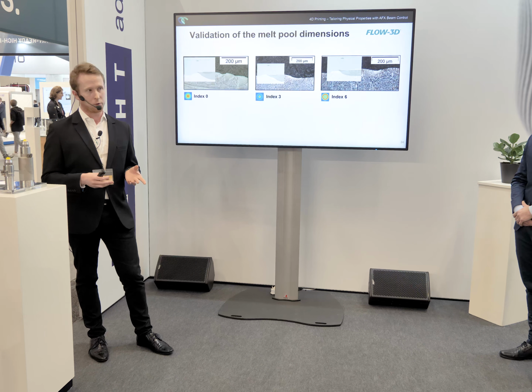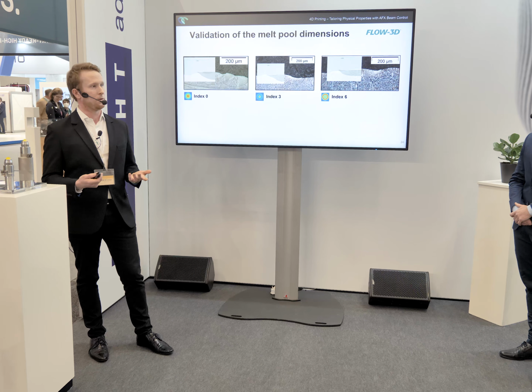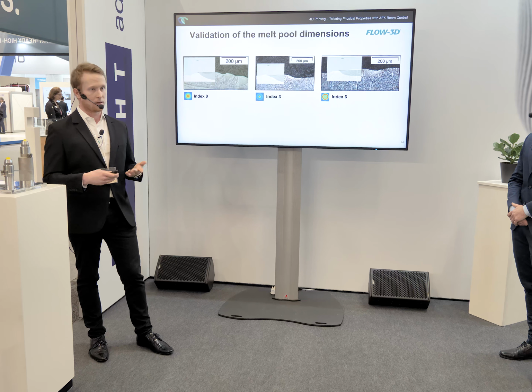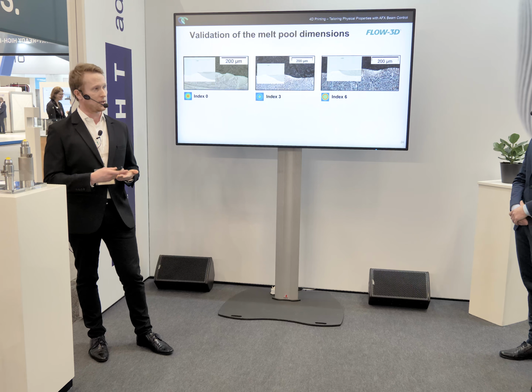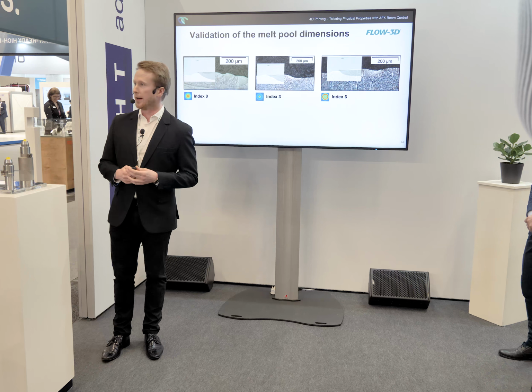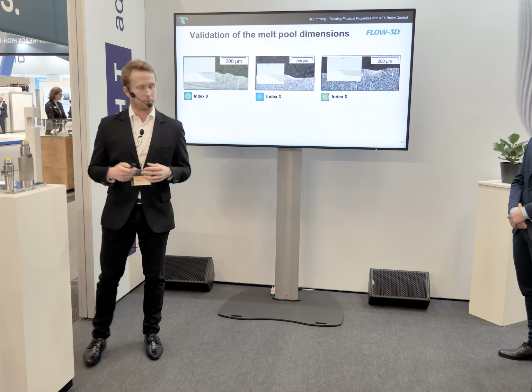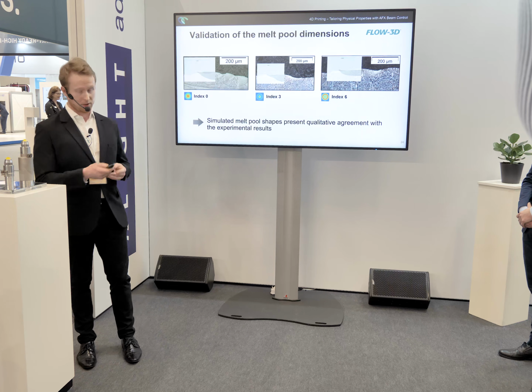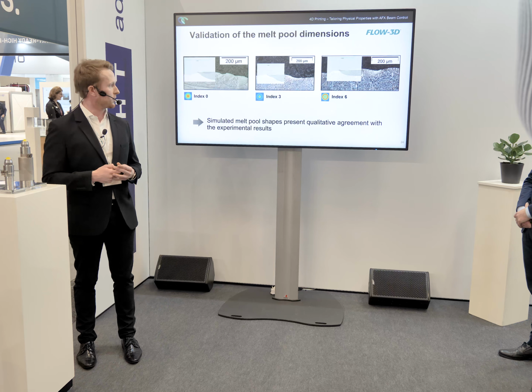And this is what we do capture in the model, which is a very positive result because it shows us that there is a qualitative agreement of the influence of this parameter on the melt pool shape. And it shows us that we're on the right track with using the model.